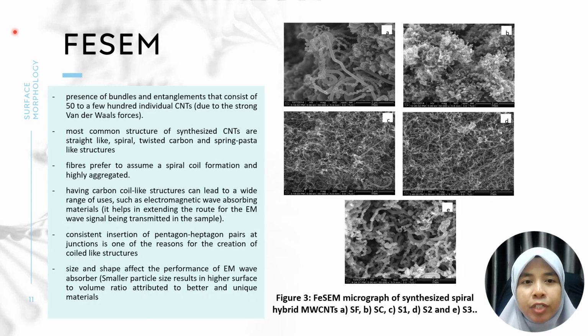Next is for FESEM, or Field Emission Scanning Electron Microscope. So this is the FESEM micrograph of synthesized spiral carbon nanotubes with SF, SC, S1, S2, and S3. So the presence of bundles and entanglements that consist of 50 to a few hundreds individual CNTs is due to the strong van der Waals forces. So most common structure of synthesized CNTs are straight-like, spiral, twisted carbon, and spring pasta-like structures.